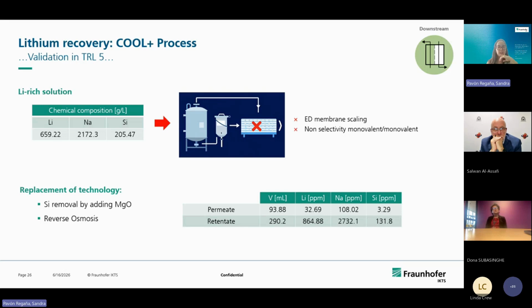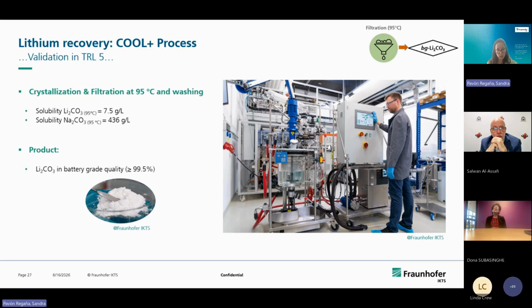I want to point out here that we also had a challenge with the monovalent membrane. This doesn't mean that it doesn't exist. We know that these monovalent membranes exist, but unfortunately, because of some exclusivity partnerships between the producer of this membrane and other companies, they were not able to provide us this monovalent membrane. That is why we have to go through reverse osmosis in order to concentrate lithium in the retentate, and then we were able to proceed with the crystallization.